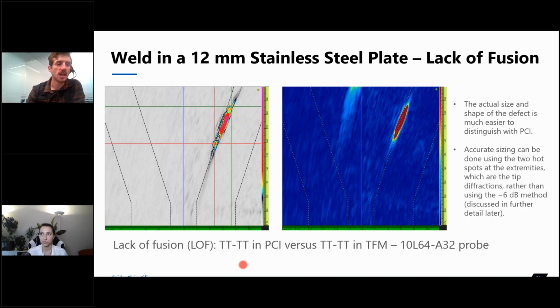So moving back to the same weld sample that we saw the porosity in, but using this time a lack of fusion. So lack of fusion, we knew it was there. We've always been able to see it. It's not particularly hard to see if you're using a probe that's correctly oriented. But one big difference here with PCI is the appearance of the tips of our lack of fusion, which are causing a diffraction pattern. So we can kind of see them.